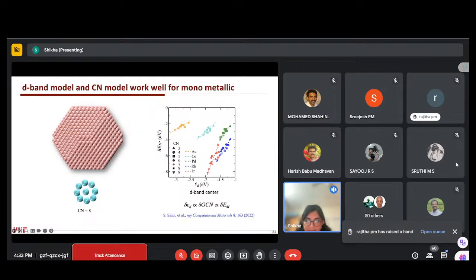So for the monometallic system, we know that the binding energy of the site correlates with the D-band center and also correlates with the change in the coordination number. So the idea is that if the D-band center shifts towards the Fermi level, like the value will be less negative, then the binding energy will increase.